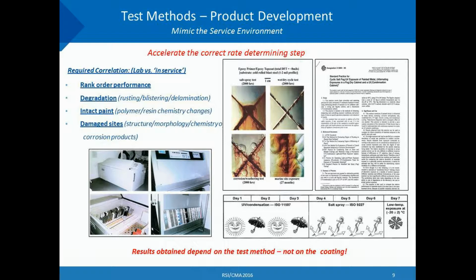And here's an example. This is just one. There are many more. But this example shows the differences, in this case for an epoxy coating, when it's exposed to different test conditions. And this one right here is the epoxy coating after 2.5 years of actual marine site exposures. And you can see that the corrosion degradation shows large blisters on the surface that are actually filled with solidified corrosion products. And if you look at what happens in the salt fog chamber for, I don't know what it is, 2,000 hours, you don't see this effect at all.